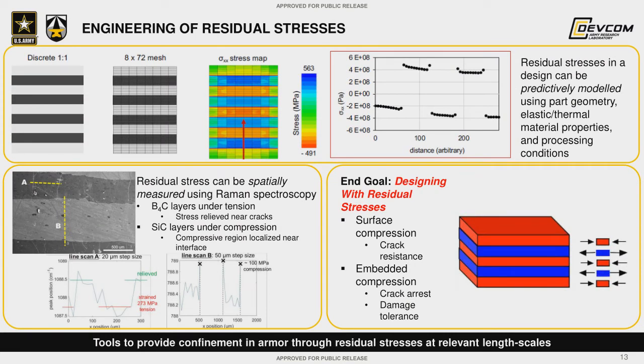So a lot of our current work is working on engineering these residual stresses in order to identify the design space we can work with and give us some ability to control the residual stresses within the material. So we've been doing modeling work using finite element modeling in order to take the geometries of the parts as well as the material properties in order to try to predict the residual stresses that will be produced during sintering, and then used Raman spectroscopy on hot pressed parts in order to see how well our models are matching up to the actual residual stresses that we see during sintering.